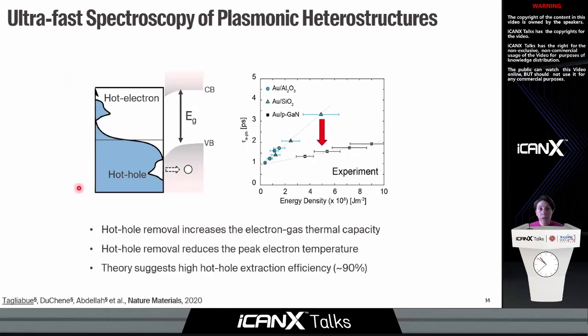So in fact, if you remember, I showed you at the beginning, this is the very prompt distribution of hot electrons and holes. Then we know we are transferring part of the holes to the semiconductor, but in a slightly longer time frame, we will have a thermalized electron distribution. And so when we are removing the holes, we know now that we are on this type of curve, while when we are on an insulating substrate, we have a much higher energy. And as you see, this is important because if at this interface we plan to have adsorbed molecules, it means that in the second case, we have a lower population of high energy electrons.